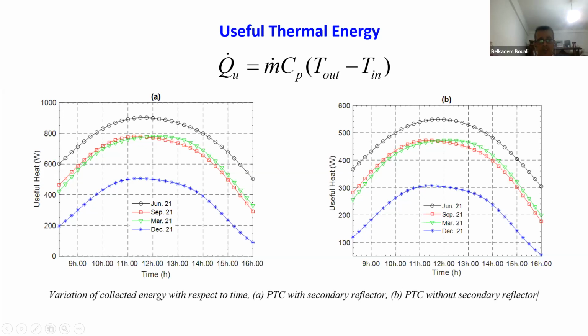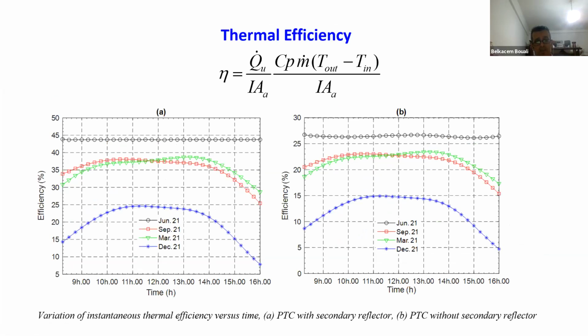Finally, the most important result is the thermal efficiency of the system shown in the following figures. For the two cases, PTC with and without secondary reflector, this parameter is calculated by the equation shown, where I represents the density of the solar flux and A represents the surface of the reflector.